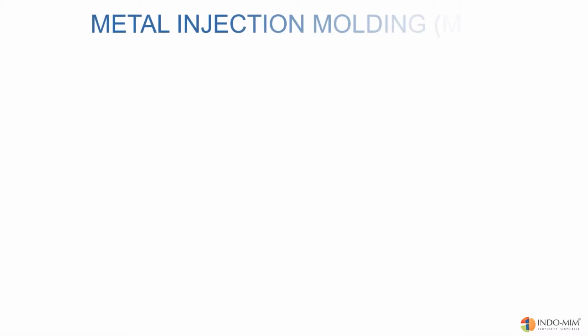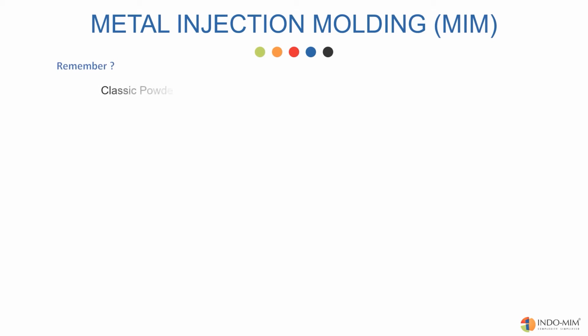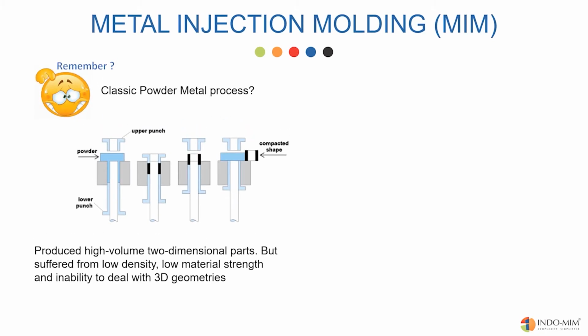Do you remember conventional powder metal process? It's also called press and sinter. In this process, we take metal powders, press them with high pressure in a die using top and bottom punches, add some core pins to produce holes, etc. The pressed parts are sintered in a furnace to get to 90% of the material density. Great process, but not good enough, because the process can produce only two-dimensional shapes and poor material properties because of low density.